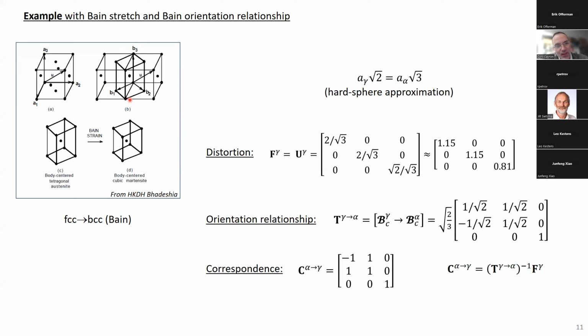So if we take this tetragonal centered cell here, it's quite easy to understand how we can distort it to make it a body-centered cubic cell. We just have to contract along this axis and elongate along these two axes here. If you do that, you can do the calculations. Okay, we can add some constraint on the lattice parameters by assuming that the iron atoms here are hard spheres. And if you do that, the distortion matrix is actually a stretch matrix. It's a diagonal matrix here, and you can do the calculation and you get this. In general, you have a matrix that is close to identity for a distortion matrix because the distortion is never very, very big.